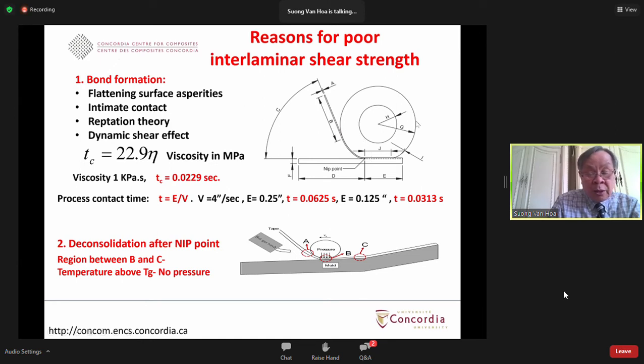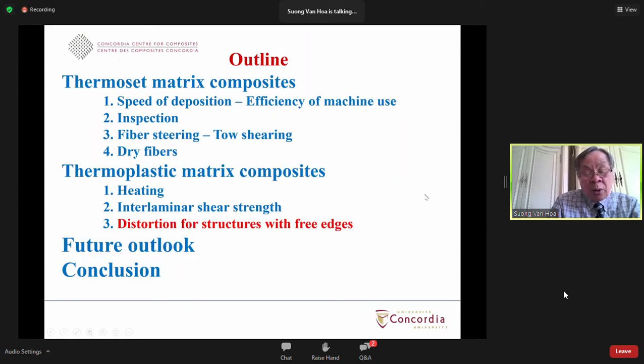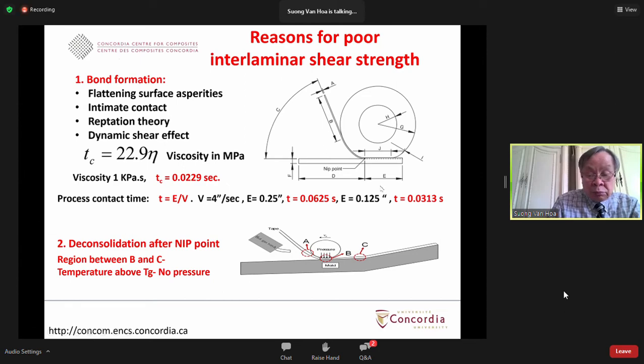So by this equation, t equals l, where l is the length of the contact, divided by v, which is the velocity of motion. If we take the speed of deposition as 4 inches per second, and l equal to say 1/4 inch for the case of a soft roller, then the time is 62.5 milliseconds. If the length here is only 1/8 of an inch, then the time is only 31.3 milliseconds, which is just barely enough, except that this time is only for the case of the reptation. It doesn't take into account the time required for flattening the surface asperities and also for intimate contact. So in this case the time of contact is just barely enough, or on the borderline, to be able to make a good bond.